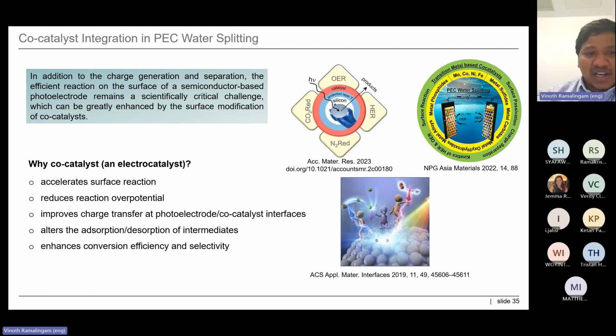In that case, we need an electrocatalyst. In case of PEC, we can call it a co-catalyst, because along with the photoelectrode, it facilitates the reactions. So why do we need a co-catalyst? The co-catalyst is really important because it can help you accelerate the surface reaction, because water splitting is a surface reaction, and it also reduces the reaction overpotential and improves the charge transfer at the photoelectrode and co-catalyst interface, so that you can get a better PEC performance.